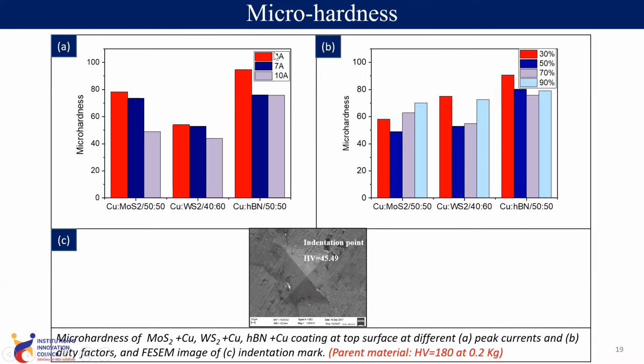So these are the micro hardness values that you can see at different duty factors, in different colors. At different duty factors, you observe that a low hardness is obtained by increasing the duty factor from 30% to 50%. A similar result is observed for copper WS2 coating and copper HBN coating. By increasing the duty factor above 50%, that is 70% and 90%, the hardness increases. Why? Because at 50% duty factor, as we have already discussed, there is a large amount of deposition. So the hardness becomes low at 50% duty factor.